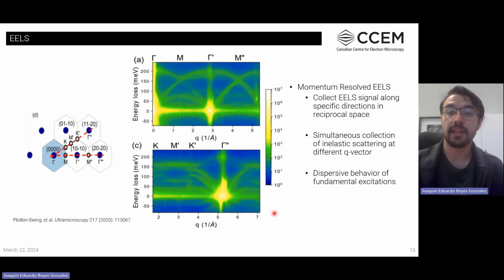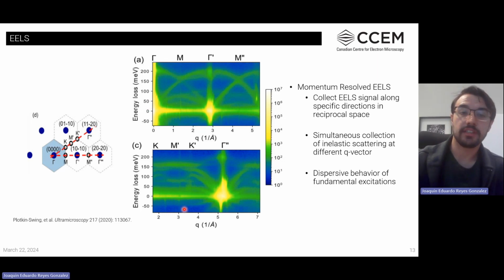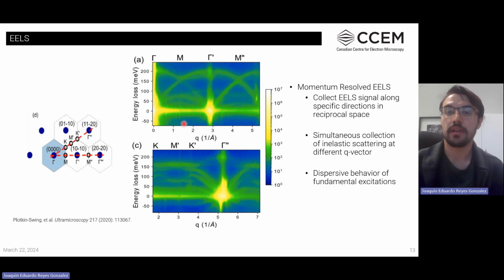This allows us to unveil this dispersive behavior and create these really interesting maps that we can see here, which for the purposes of these images are associated with the phonons of hexagonal boron nitride. You can see all these branches can be associated with different phonon modes that exist on the crystal.